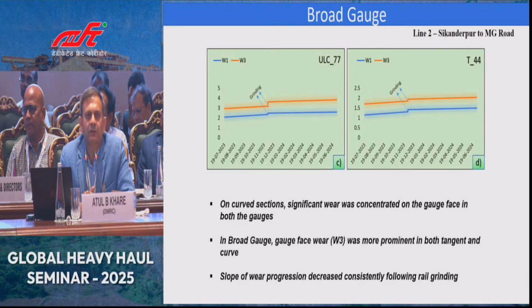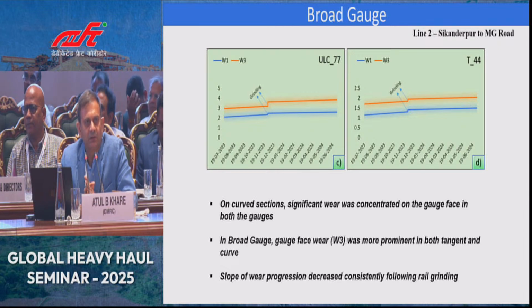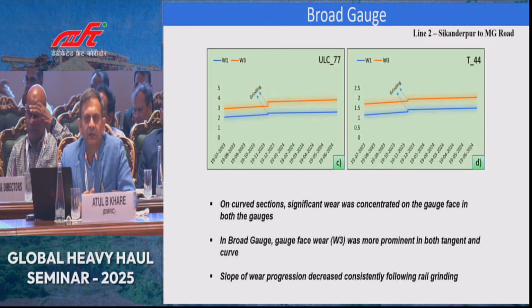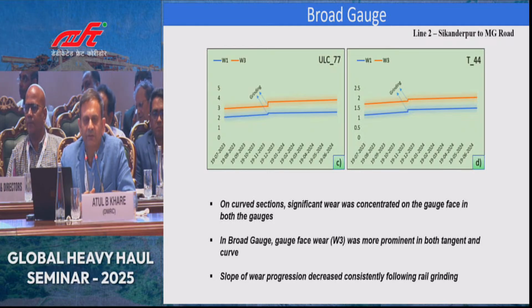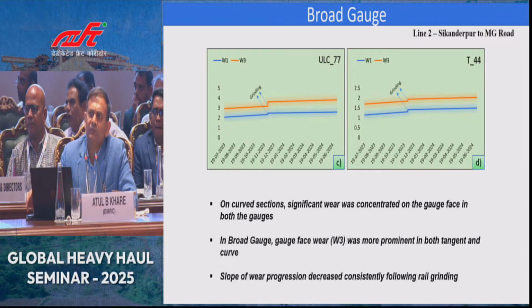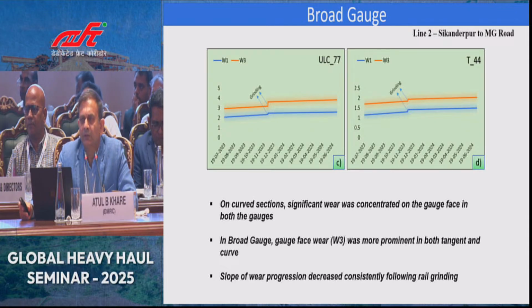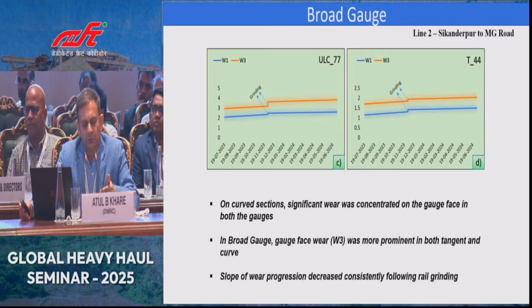We are measuring results on the test site before establishment of test site, after the passage of grinding at test site, and after some passage, maybe about a year or maybe 6 months, at those test sites. So we have observed wear with respect to the Miniprof, and the wear observed on various test sites has been plotted, and I am presenting 2 test sites on broad gauge and 2 test sites on the standard gauge. And one of each is on sharp curve and one is on straight track, tangent track.